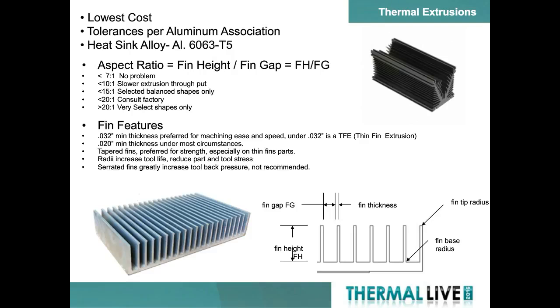An aspect ratio less than 7 is very straightforward. Generally, those push without too many problems unless you run into thin material. Less than 10 may require us to slow the process down so that we can reduce any damage to the tool that we may have. Shapes that are greater than 10 require a lot more care in terms of both the tool design and its operation to make sure that we give you a good product. Now, typically, these aspect ratios are good for extrusions that are less than 8 inches in width. Wider extrusions play by a different set of rules, and those usually need to be evaluated on a case-by-case basis.